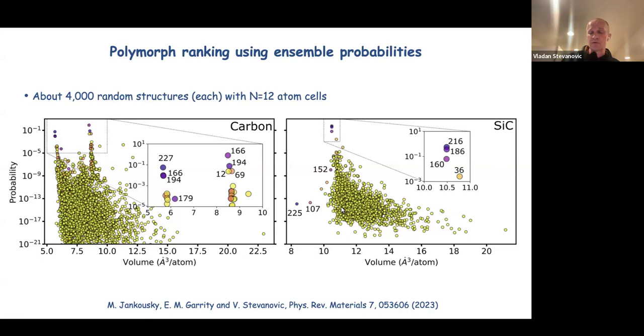The silicon carbide distribution of probabilities is markedly different. It has only one peak now. And at the top of that peak, what you find are, again, expected structures. You find space group 216, which is the zinc blende, followed by wurtzite, which is another known polymorph of silicon carbide, and the space group 160. That's another known polymorph of silicon carbide. And again, they are well separated from the rest.